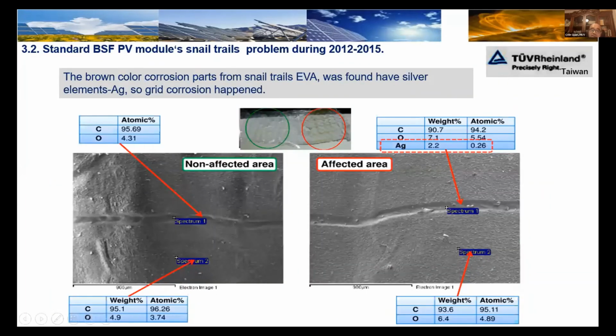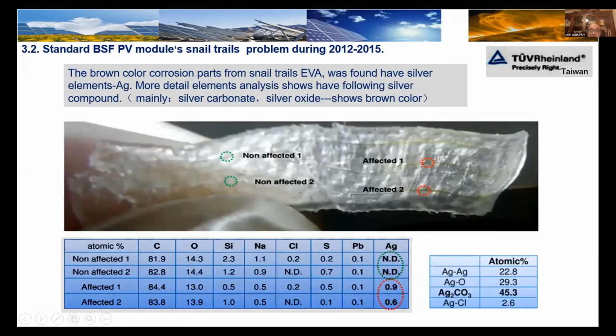You can analyze this affected area and non-affected area at the element level. Okay, they can find here there is some silver element here. In the non-affected area, they do not have silver. That's only here. This part, a little bit far from here, does not have silver. This is where the grid finger exists. So they did some more detailed tests to see what it really is. They tested it, and it is silver carbonate and silver oxide material here. This material can make it show a brown color. So mainly it's a silver carbonate material here.